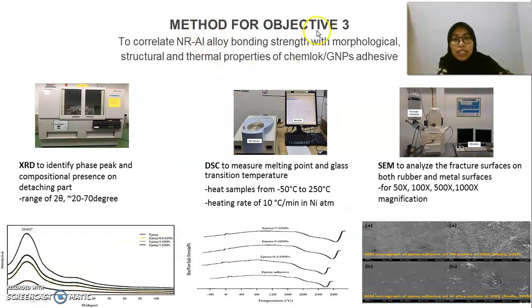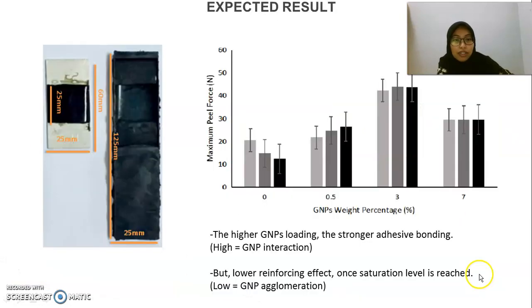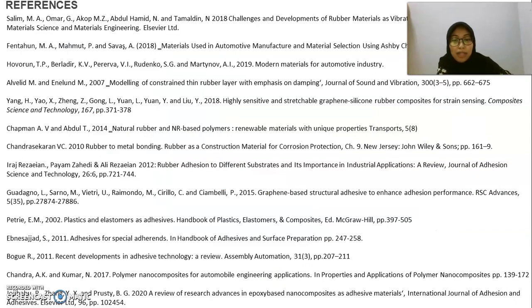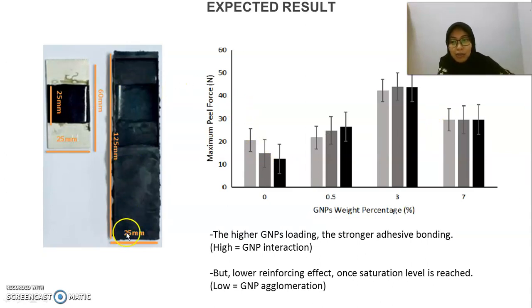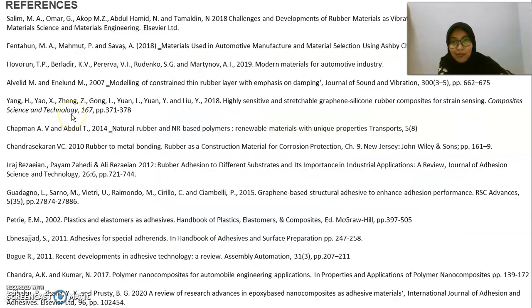The method for objective 3 considers XRD to identify the phase peak and DSC for thermal analysis, which is glass transition temperature and melting point, and next is SEM for the fracture surface of both surfaces. The expected result shows that increasing GNP shows increasing maximum peel force, showing the GNP interaction, but a lower reinforcing effect once the saturation level is reached, which shows GNP agglomeration. So this is the rubber parts dimension, aluminium, and adhesive. With that, thank you.